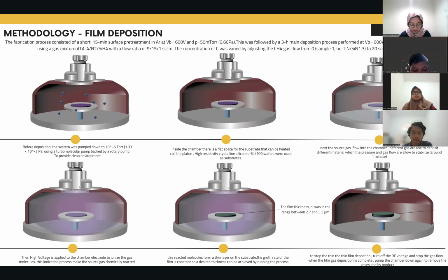So this ionization process makes the source gas chemically react. After that, the reacted molecules form a thin layer on the substrate, with a constant growth rate of the film, and a desired thickness can be achieved by running the process. From this process, the thickness of the thin film ranges between 2.7 and 3.3 micrometers.